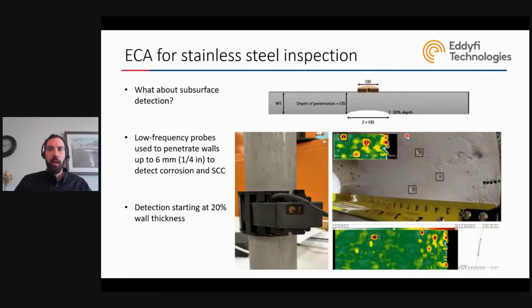And finally, this is a very new type of inspection that we can do with the spine, because we just launched this low frequency probe that can penetrate through up to 6 millimeter of stainless steel. So for any type of stainless steel walls, 6 millimeters and less, we are able to use the coils at a lower frequency, make a magnetic field that penetrates through the wall, and you are able to detect basically any type of missing materials. It could be SCC, it could be cracks, weld flaws, corrosion, again, large pitting. So you don't have the same type of resolution, obviously, as on the top side, but you are able to find down to 20% depth any type of surface flaw.